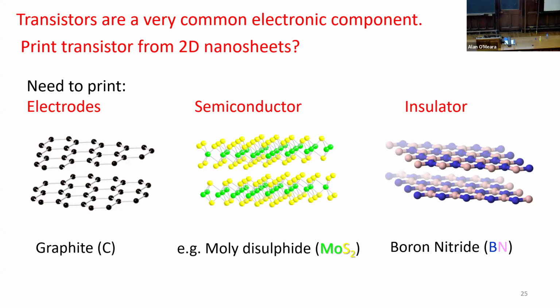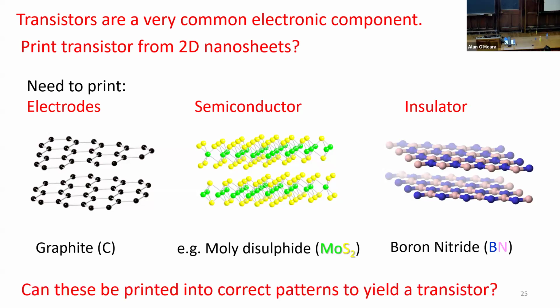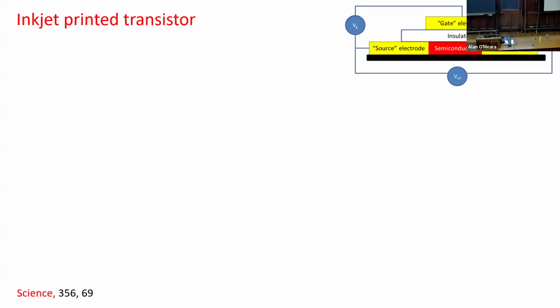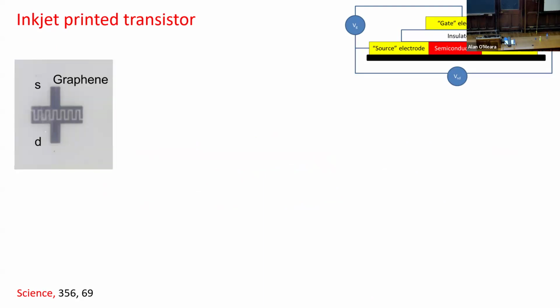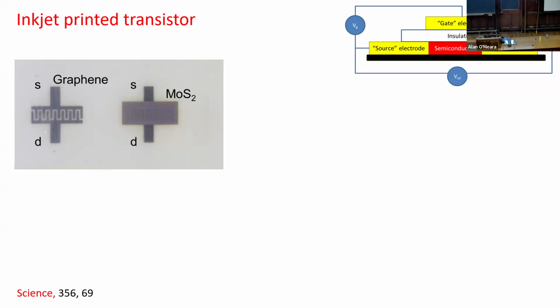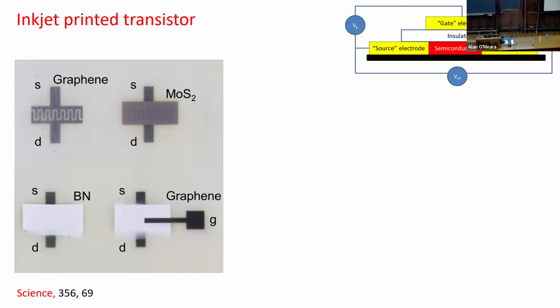So we've got all of those and we can make inks from them. So now it's a question of printing these inks into the right patterns to make the structure that defines a transistor. Now, so how do we do that? So there's the structure that you'll see in a textbook, for the aficionados, that's a MOSFET. This is the graphene source and drain electrodes. Then we printed on top of that molybdenum disulfide, which is a semiconducting 2D material. Then on top of that, we printed boron nitride, which is the insulator. And then on top of that, more graphene, which is the gate electrode.